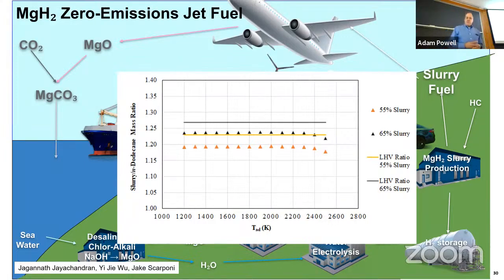So for a given mass of this slurry, to reach a given temperature, you need a larger mass of the slurry than of the jet fuel, but not as much as you'd predict based on the lower heating value ratio. And that's because magnesium burns more efficiently. It holds onto the oxygen more tightly, whereas CO2 decomposes into carbon monoxide and oxygen. Water decomposes into hydrogen and oxygen. So you don't get the full energy out of it. And that's especially true at high temperatures, but even at lower temperatures as well. You have a lower mass ratio.